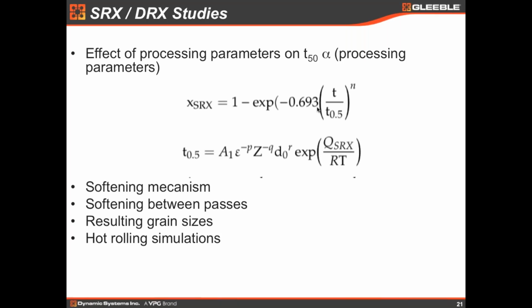Yes, the Gleeble obviously has a good thermal control, so you can simulate essentially any annealing process that you would like. So you can use a Gleeble to simulate the batch annealing process of a steel coil. Now, the difference between batch annealing and continuous annealing is usually that in a batch annealing process, you're putting the entire coil in a furnace. So you have actually very different thermal profiles that occur in a coil in a batch annealing furnace, whether you're on the outer lap or the inner lap.